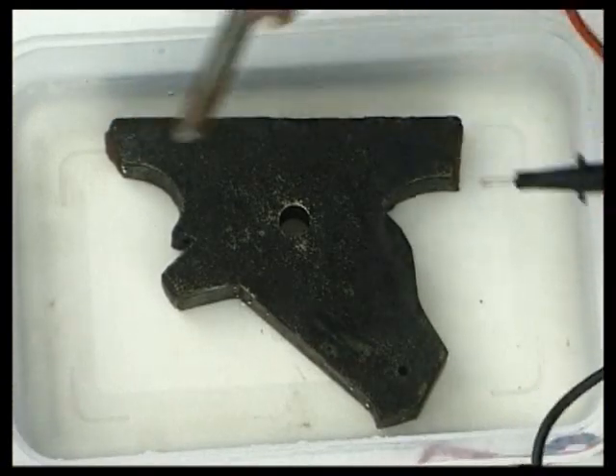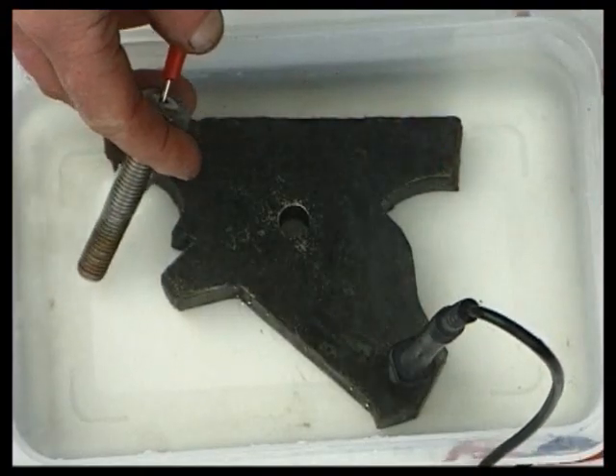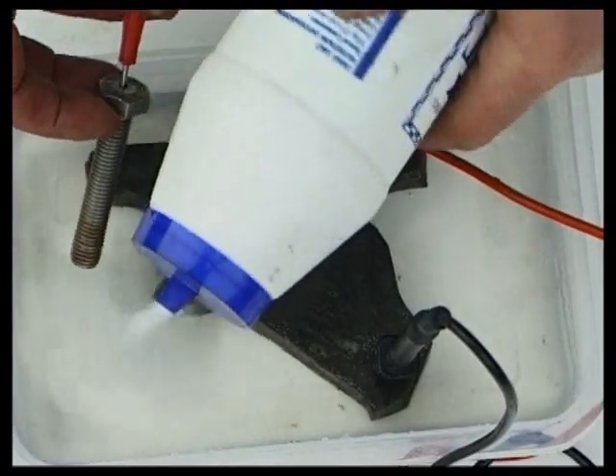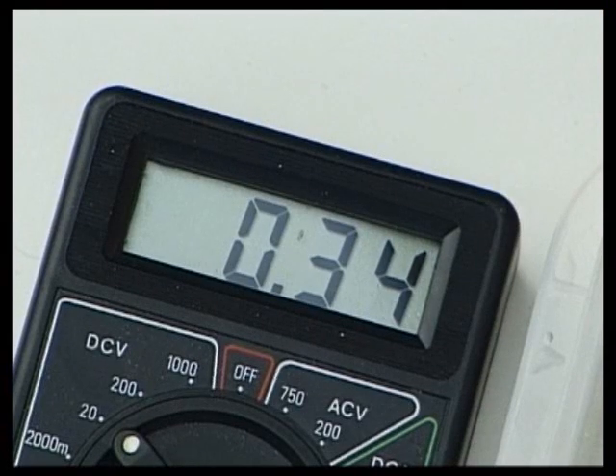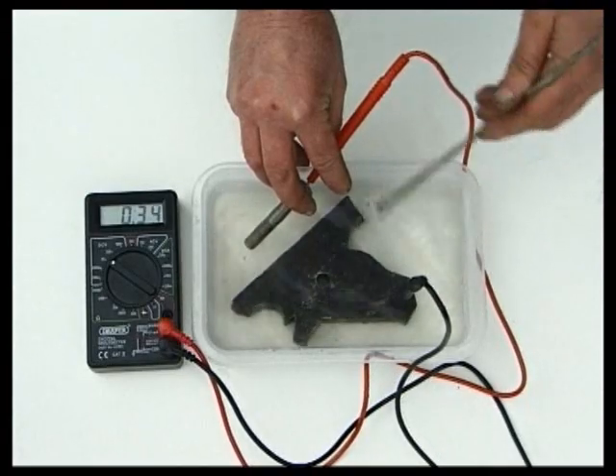Any stainless steel bolts or plates must be insulated from the iron. There is electrolytic action between the different metals, which increases with pollutants like salt. Cast and wrought iron are both sacrificial to stainless steel and will corrode away in damp conditions.